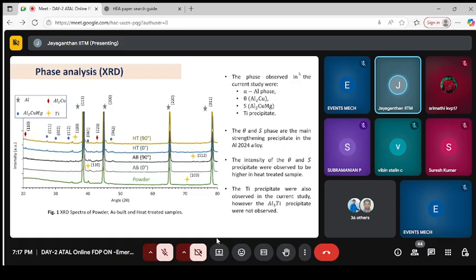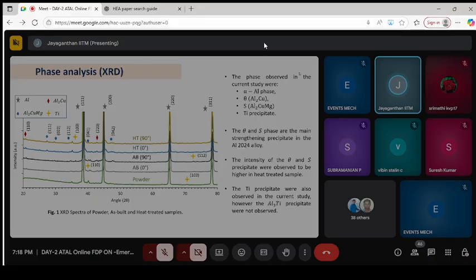And again, looking at the precipitate, what precipitate is formed contributes to strength. You are all aware that if you have a sharp edge corner, it is going to act as a stress raiser. In the same way, if you don't control the size and shape of the precipitate in the material, that is going to act as a stress raiser. That is going to be detrimental for the component you are going to make. Any component when it fails, we do root cause analysis: how has the component failed? Is it due to design or due to the way the material was fabricated? Very often we end up saying the material microstructure was not properly controlled.